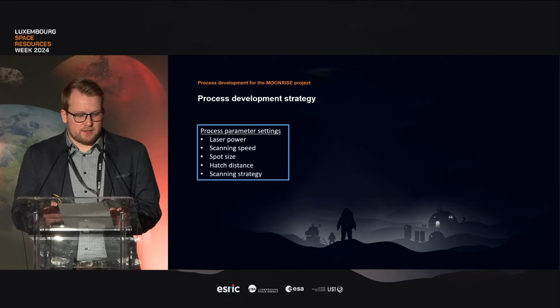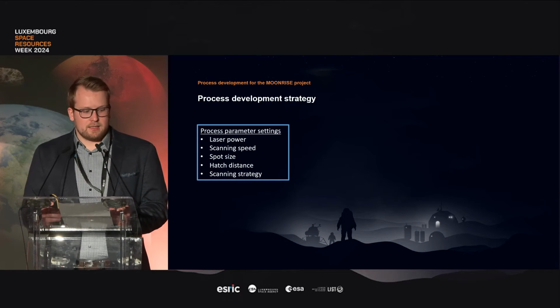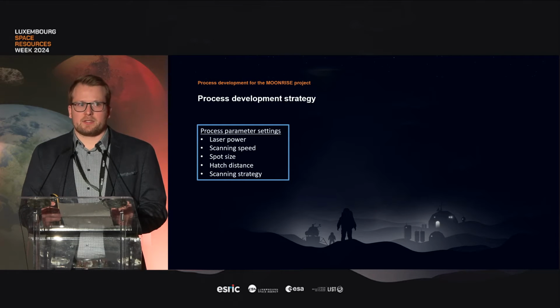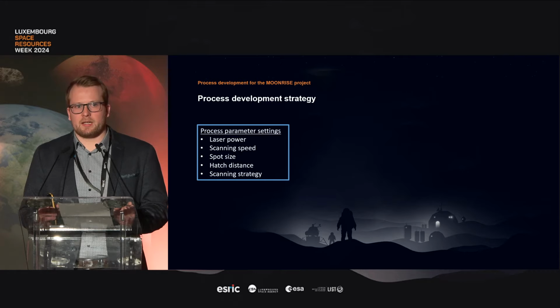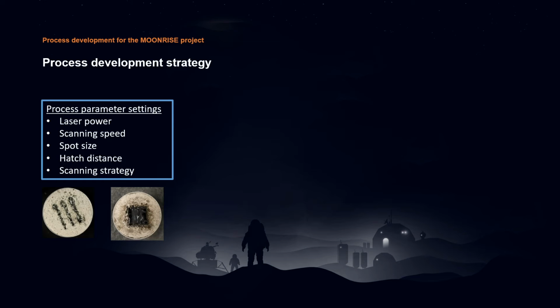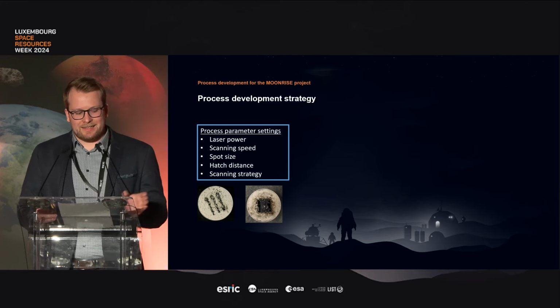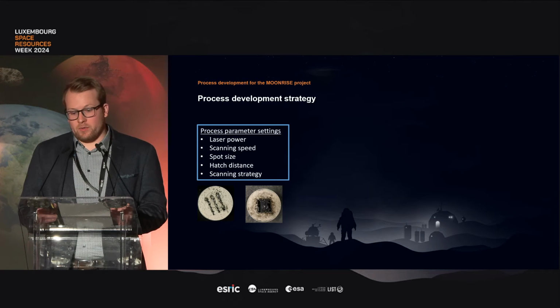And for that, we start with developing the process parameter settings, such as the laser power, which is between 100 and 150 watts, the scanning speed, which lies between 1 and 2 millimeters per second, and the laser spot, which is dependent on the working distance, but normally lies between 0.9 and 1.6 millimeters in diameter. To develop these parameter settings, we use one-dimensional samples, as you can see here on the bottom left. These samples are 30 millimeters long, and we use them because they are much easier and faster to produce than the two-dimensional ones that we will want to produce on the moon.